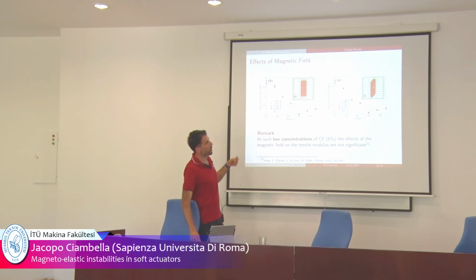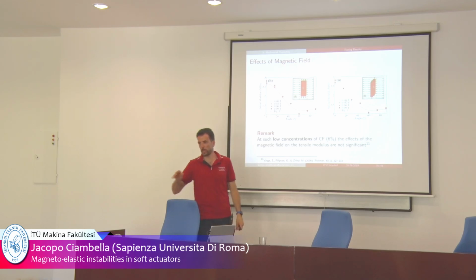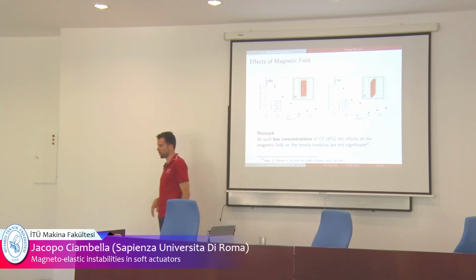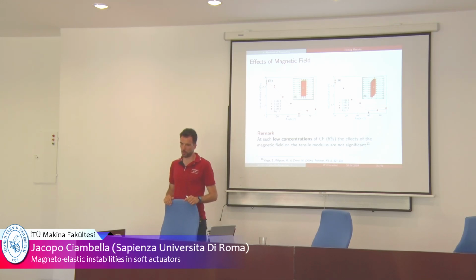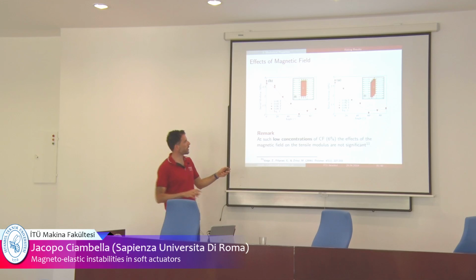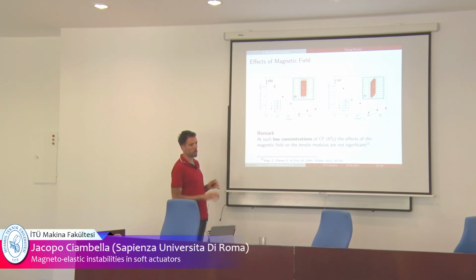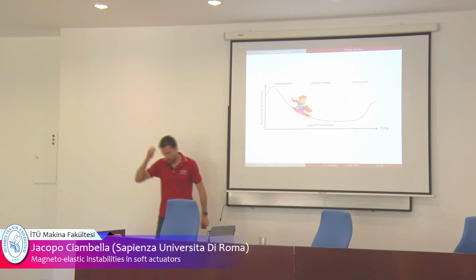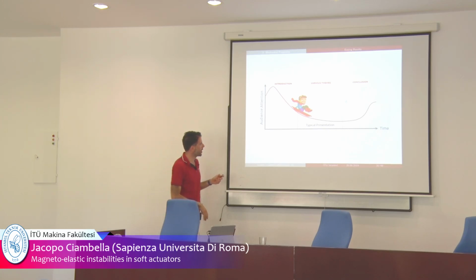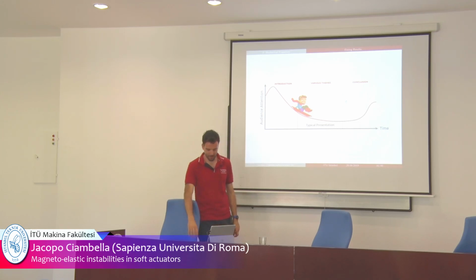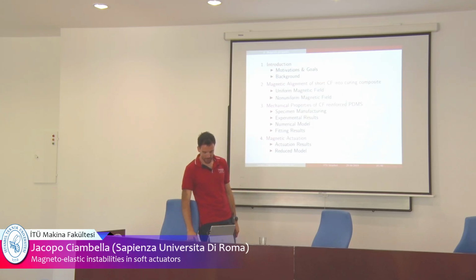Okay, does it affect the magnetic field? We didn't see, in terms of Young modulus, any significant effect. We tested the material, but we didn't see any significant effect in terms of Young modulus. Okay, so what we did, the tensile test under magnetic field for different orientation. But in terms of effect, up to almost 0.1 Tesla, there was no significant effect. Okay, we are almost done here, so we are probably here. Now I try to draw your attention on this loop, okay, by showing you this result.